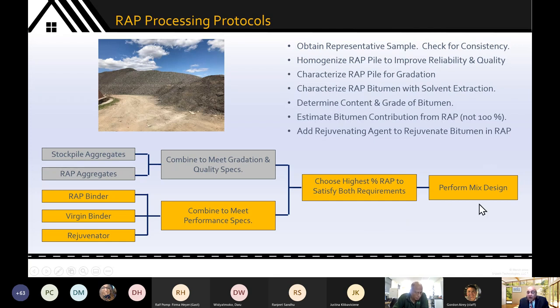We all know the typical tests that you do on incoming materials for aggregates and for virgin binder. What are some of the tests that you would do on RAP binder? Well, you check the RAP pile for gradation. You classify it according to particle size. You check it for extracted bitumen, how much bitumen content is there in the RAP, and what is the grade or the quality of that RAP bitumen.